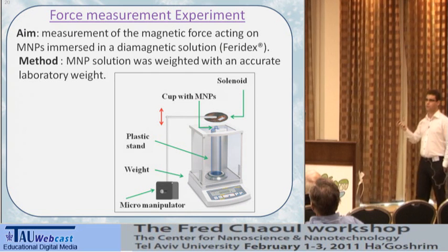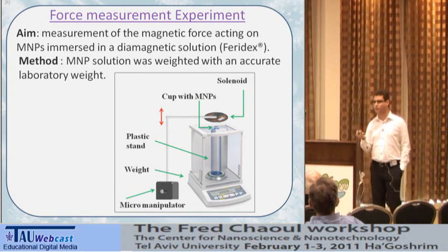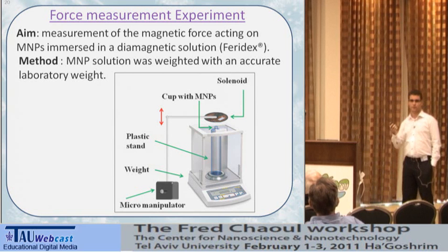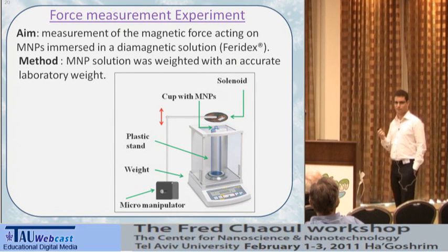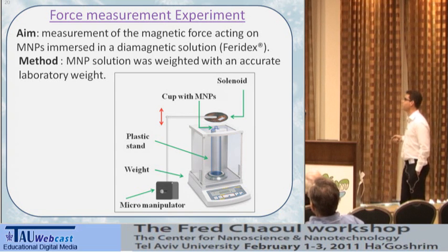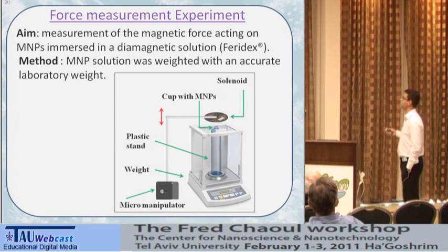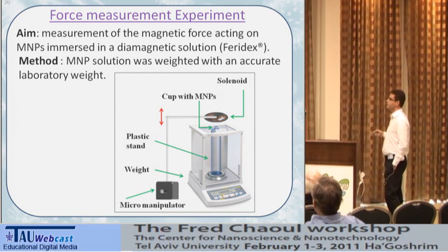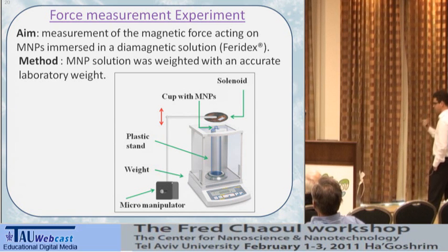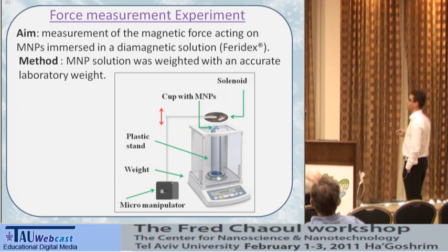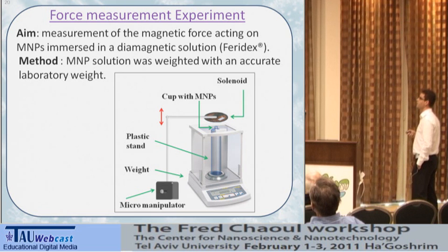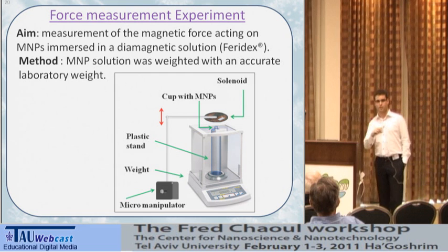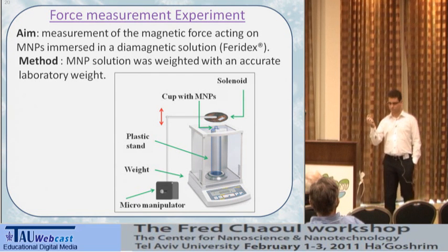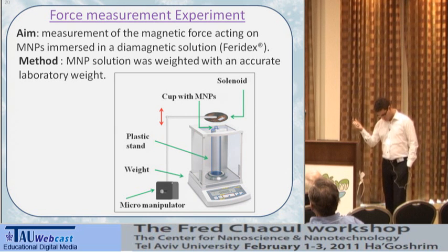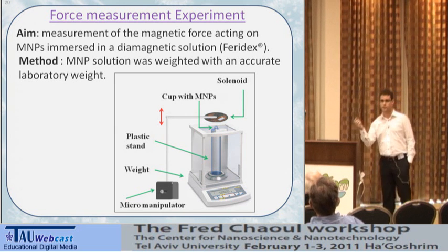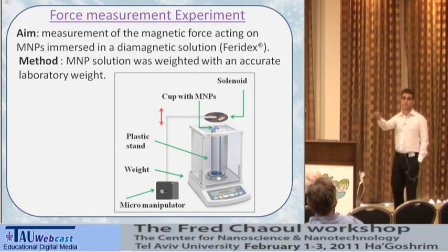The first one, we wanted to measure how much force we can actually apply. And this force is on the order of micronewtons, so it's a bit tricky to measure. What we did, we took a laboratory weight, a very precise weight. We put some plastic stand to distance the solenoid and the nanoparticles from the weight itself. We put here an Eppendorf tube with a Feridex solution, which is a solution of magnetic nanoparticles in saline, a diamagnetic material which is compatible with human blood. You can inject it into the blood.